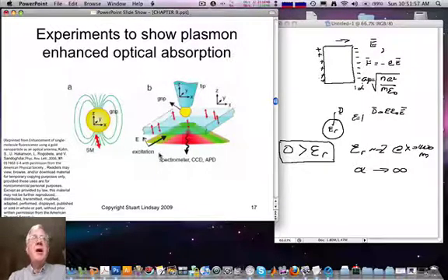However, if the electric field enhancement is big enough, it can lead to a much larger rate of absorption by the dye. The cross-section of molecules is very small, and this then in turn, because of the principle of detailed balance, leads to much greater fluorescence emission. So is it possible to overcome quenching by a metal with enhanced fluorescence?